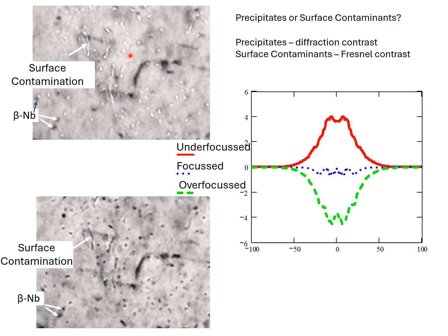Now, the more circular ones, which you might mistake for a cavity, also show up the same way, bright or dark. The reason there are two points here is this: if one is examining a material and sees Fresnel contrast, one might say, oh, this is a cavity in the material. Not necessarily.